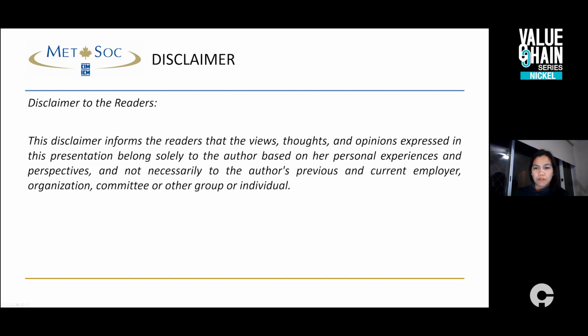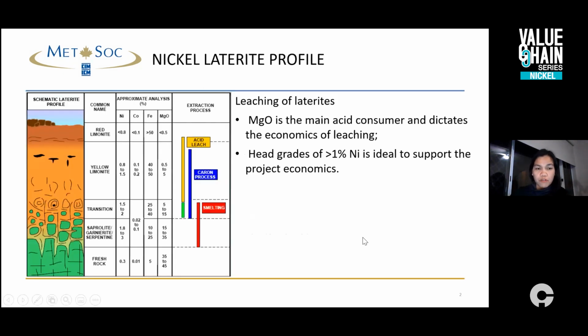So let me go through some of the slides that I have prepared, just to set the context and the setting for HPAL. You're all familiar with the nickel laterite profile. The lower grade nickel laterites are more amenable to leaching, primarily because the magnesium content is much lower. Magnesium is the primary acid consumer that dictates the economics of leaching. So when you select leaching as the extractive route for nickel laterites, the grade has to justify the economics. Particularly with HPAL, which requires more extensive capital intensity, a head grade of greater than 1% nickel is ideal.